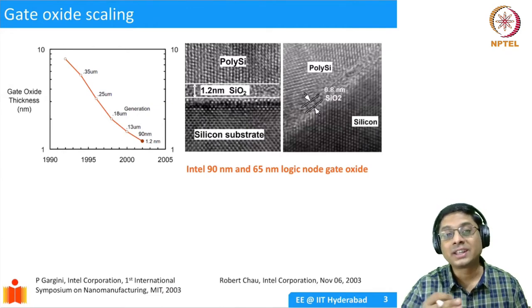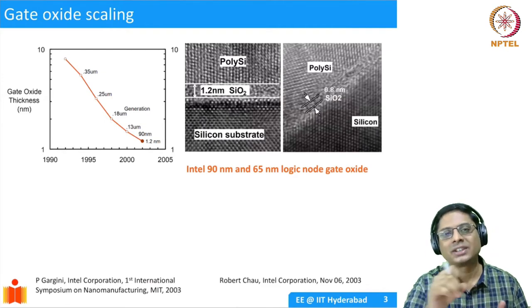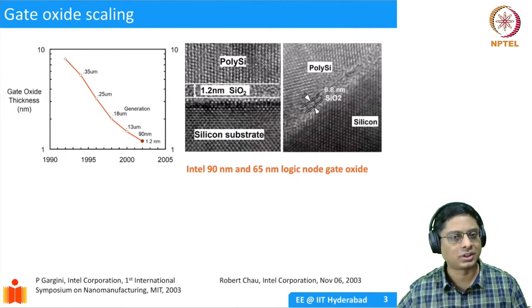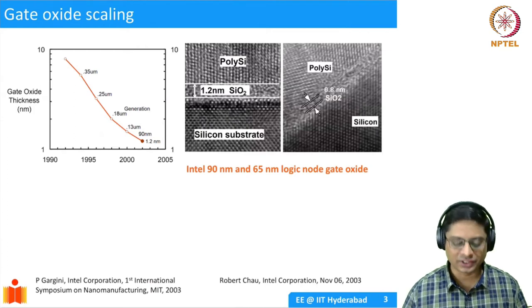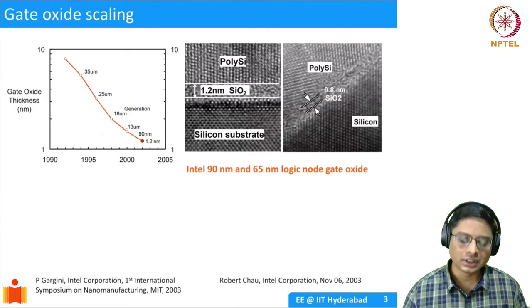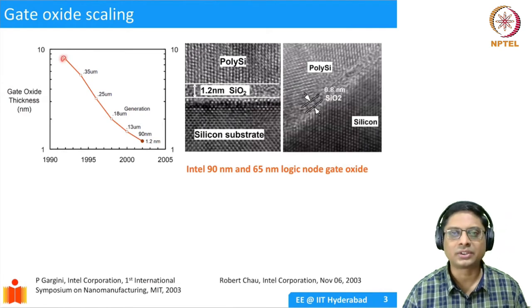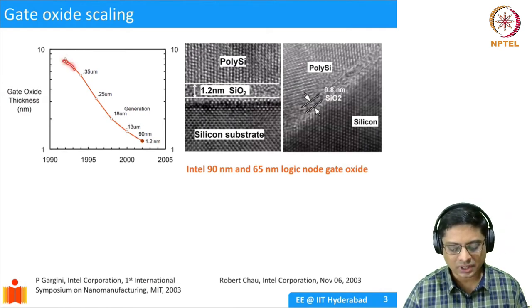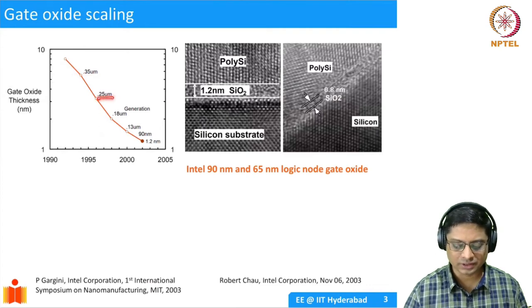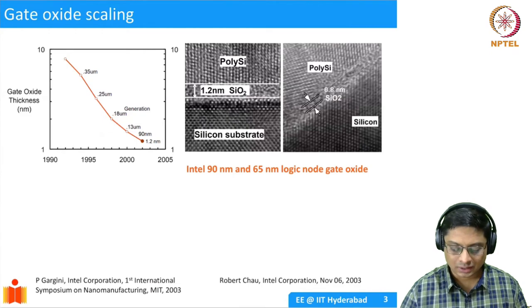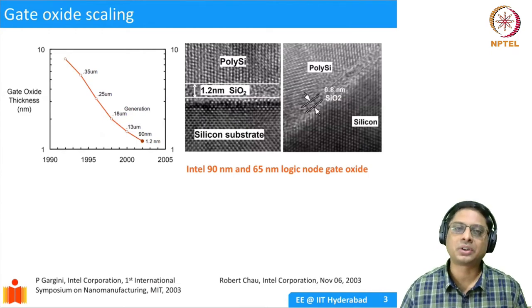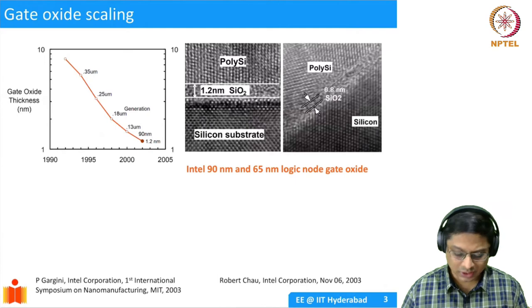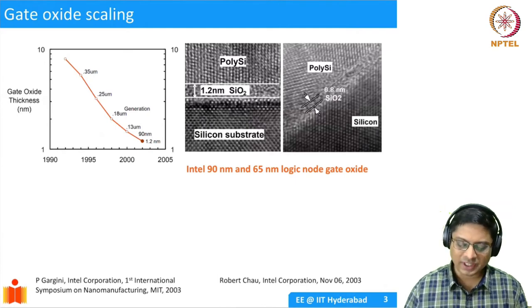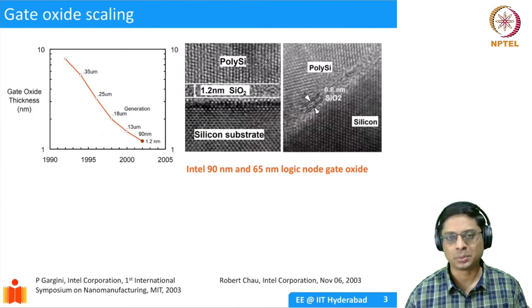So in a way, we are scaling. We are multiplying the gate oxide by a certain number, and then we are making it smaller and smaller. This is what happened in the semiconductor industry over the last 30 years. Essentially, we start with some thickness of oxide, and as you come down, the thickness gets smaller. This is called 350 nanometer technology, 250 nanometer, 180 nanometer, and by around 2003, we were at a point where the thickness of silicon dioxide was 1.2 nanometers.